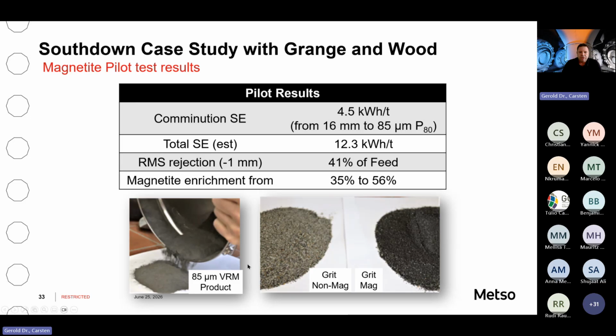So giving some more numbers from the pilot campaigns that led to the project. Within the pilot test work, we even achieved a higher rougher magnetic separation rejection of 41%, but for the business case, that was reduced just to be more on the conservative side. But the magnetite enrichment that could be achieved simply in the grinding, you could increase the magnetite from 35 to 56% as part of the grinding. And that really simplifies your process, and it highly extends your dry processing.